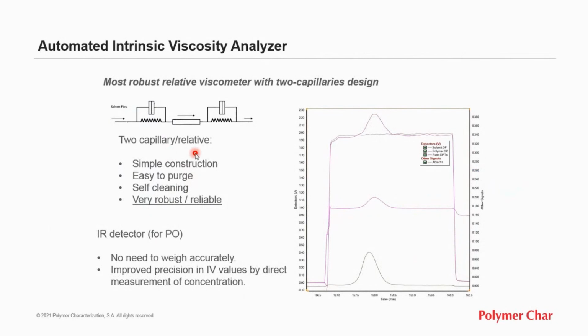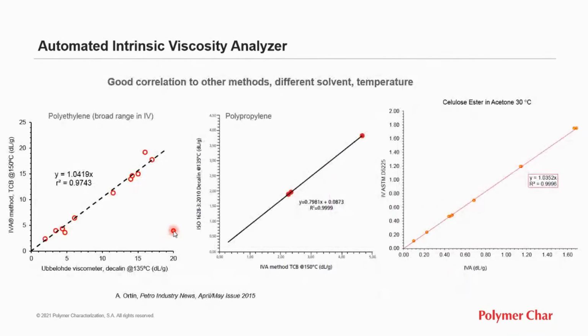It is based on a very robust two-capillary relative viscometer detector. And for polyolefin applications, the infrared detector is coupled and is useful to quantify the amount of polymer injected, so there is no need for accurate weighing. In different applications, we found good correlation to existing alternative methods for polypropylene or polyethylene, comparing to the ISO 1628 method. And also recently we ran some analysis of cellulose ester in acetone at 30 degrees compared to other methods, and the results are well in line.